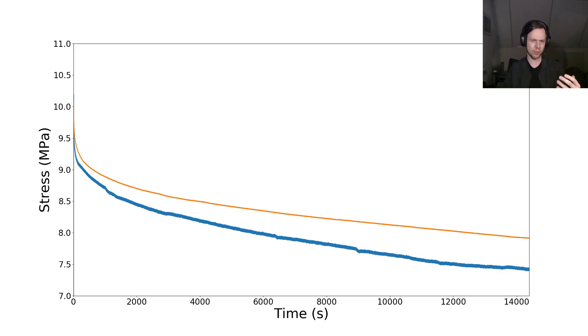This could either be because of edge effects, where the first few layers of the sample that has been printed and the last few layers of the sample as printed don't contribute quite as much to the strength of the material. And the other possibility I see is that there may be inhomogeneities in the material due to the fact that it's printed. And those inhomogeneities weaken the sample, but that effect is stronger if the sample is very thin.